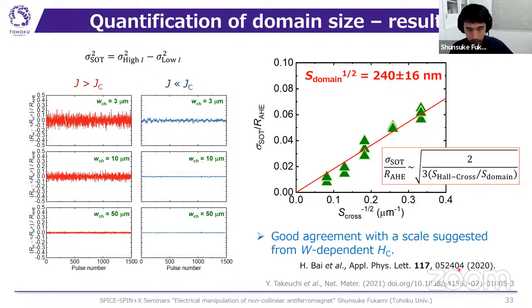And recently, Chen's team studied the width dependence of the coercive field, and they said that the coercive field decreases with decreasing the width, and it implies that the domain size dominates such behavior. And according to the explanation, the domain size is somewhere around a few hundred nanometers. So our result is consistent with their implications.